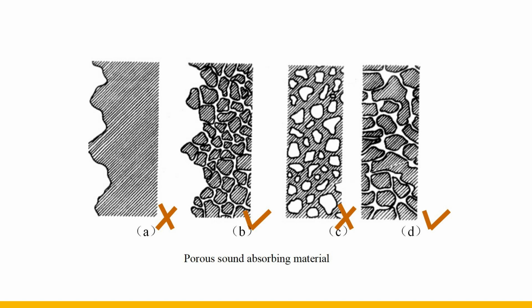It can be seen from the figure on the left side. With the increase of thickness, the sound absorption coefficient of the medium and low frequencies increases significantly. The high frequency does not change much, and the total sound absorption increases. It can be seen from the figure on the right side. If the thickness is unchanged and the density is increased, the sound absorption coefficient of the medium and low frequency can also be improved, but the flow resistance will be increased. It can be seen that the density also has an optimal value, but the effect is not as good as